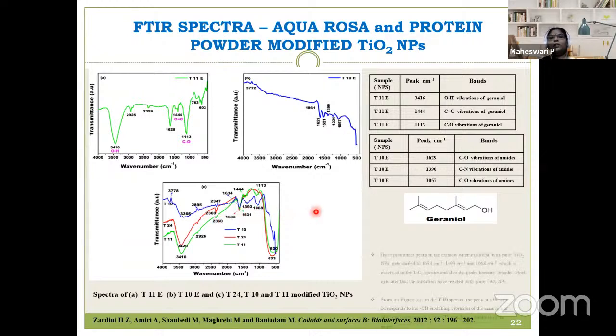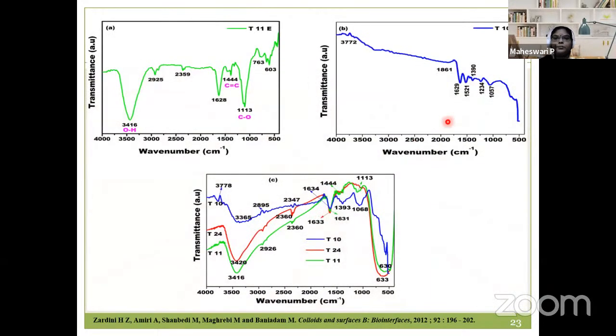Now I have taken another picture to show this. So this is the one. Now you can see from these two parts, the red line is the synthesized TiO2, the green indicates the aqua rosa modified, and the blue gives you the protein powder modified. You can see more or less the aqua rosa and the TiO2 are at the same level, but you can see there is a difference in the fingerprint region, and also a change in this particular region. There is a broad peak.